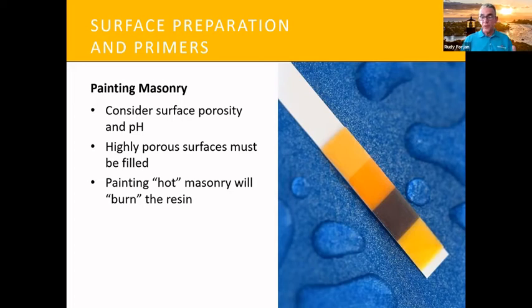So latex paints will allow moisture vapor to pass through, but it will not allow the salts that the moisture has solubilized. So that will tend to collect behind the coating itself. That will cause an adhesion issue with the coatings on masonry. So you really have to make sure that you're doing it correctly, and that pH is not going to be the biggest problem, that hot masonry kind of problem.